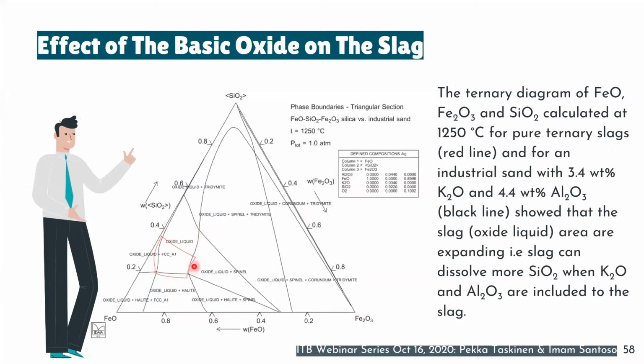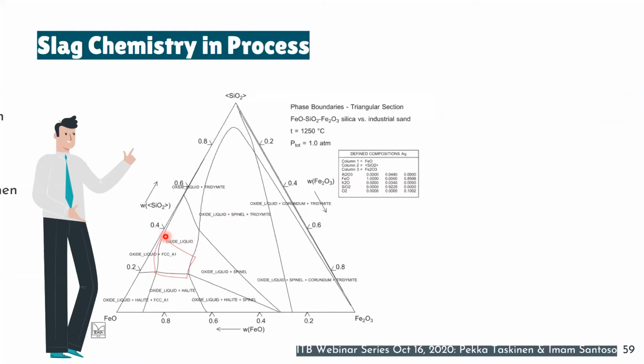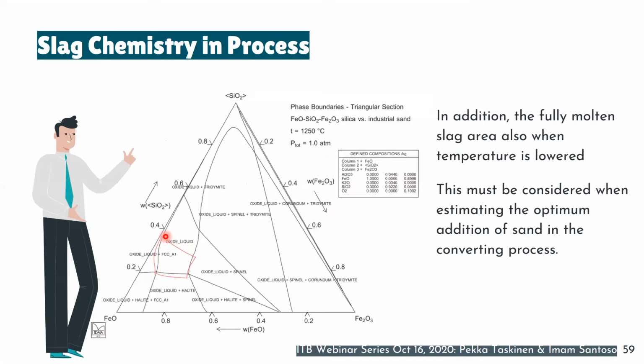So the red line is when the slag doesn't contain any potassium or alumina, or it is pure iron silicate slag. So we can see that the stability of the slag again becomes larger. And in addition to that, when we decrease the temperature, the liquid slag area also becomes smaller. So we have done a lot to get the optimum condition in the converting process. It is temperature, it is also impurities.